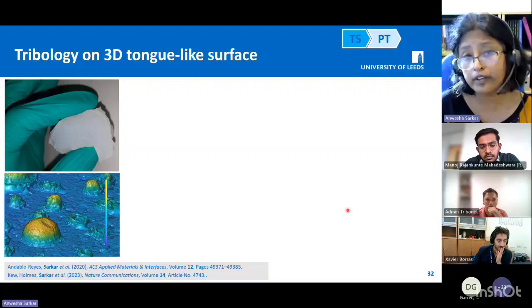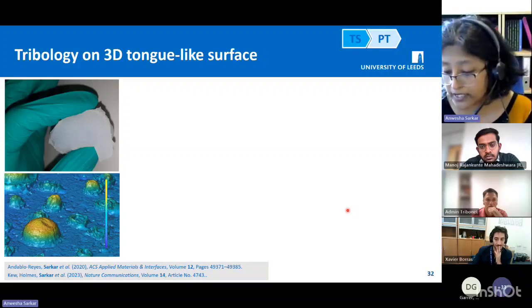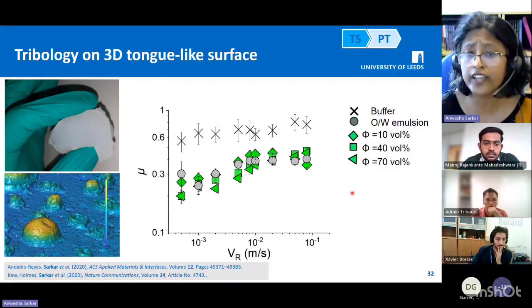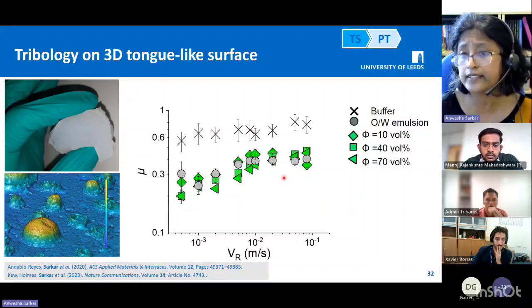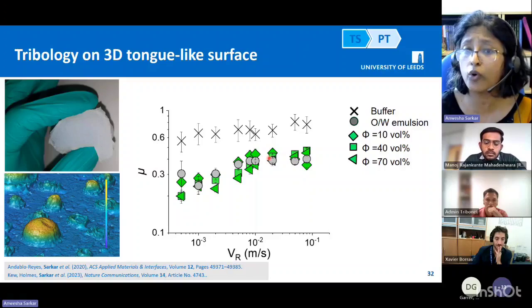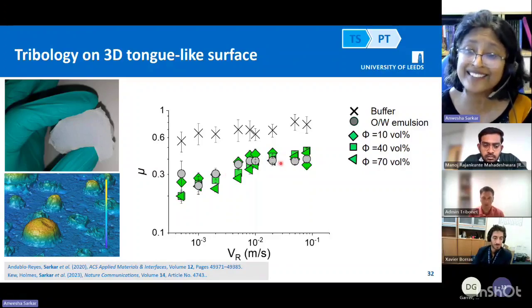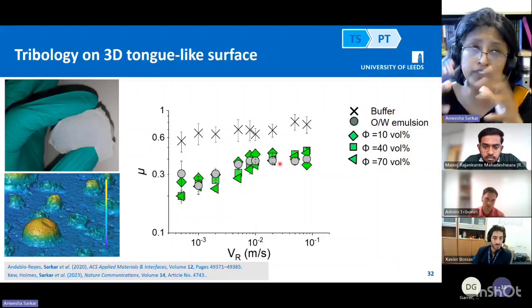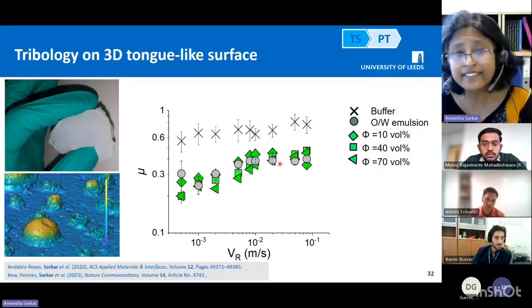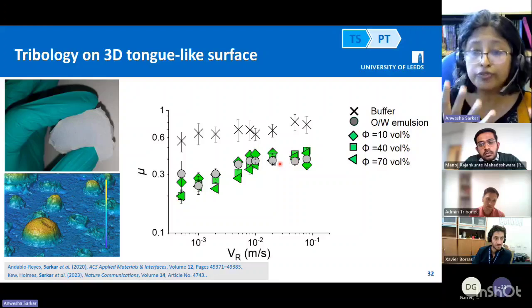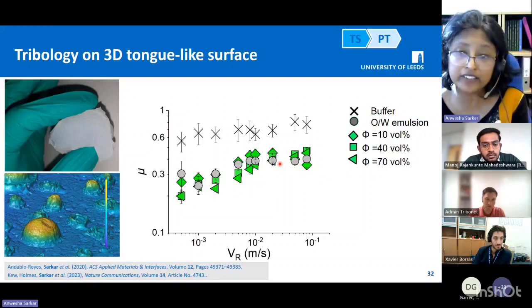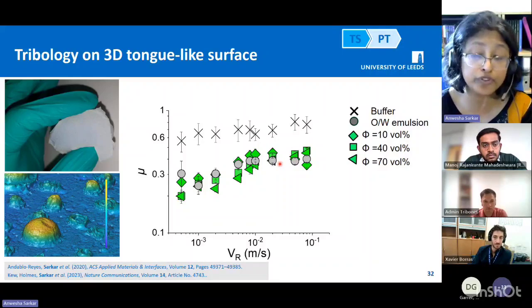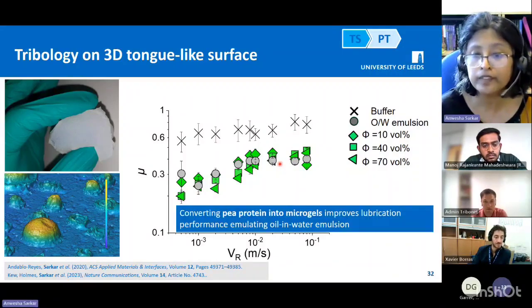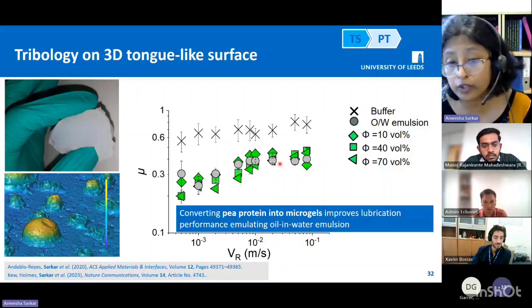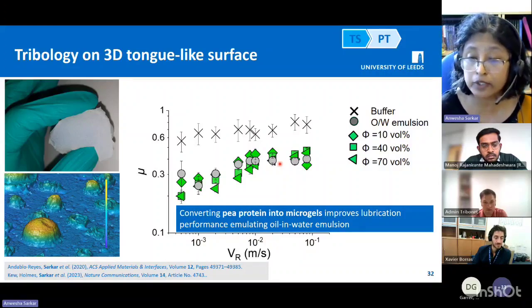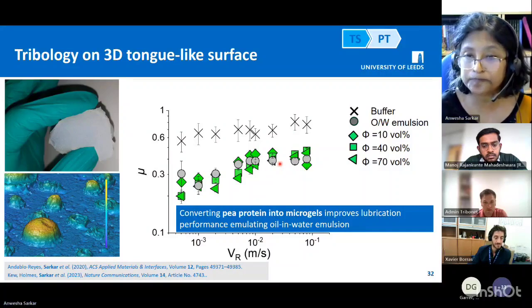So now we took the microgel and put it in a 3D biomimetic tongue-like surface, and we saw exactly the same behavior: the microgel was behaving like an oil and water emulsion without adding a single drop of oil. That means you have converted an astringent molecule into a fully creamy material without adding a single drop of oil, which was very, very exciting. So it indeed improves the lubrication performance, emulating an oil and water emulsion.